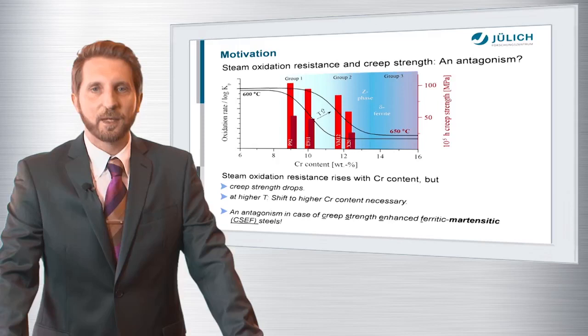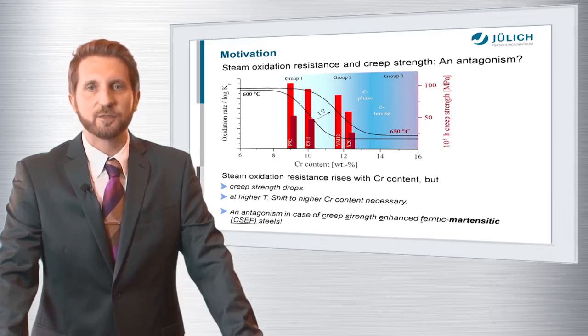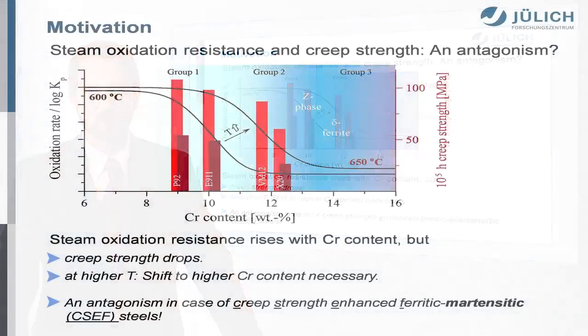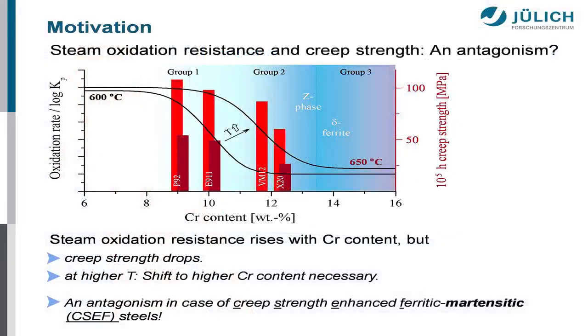As we want to go up to higher temperatures of about 650 degrees C, you see that if you want to maintain sufficient steam oxidation resistance, you have to go up in chromium content. And this even sharpens the problem with the drop in creep strength with rising chromium content. And that is, for example, due to Z-phase formation and delta ferrite formation, which troubles you with complete martensitic transformation upon cooling, and that leads to the drop in long-term creep strength.